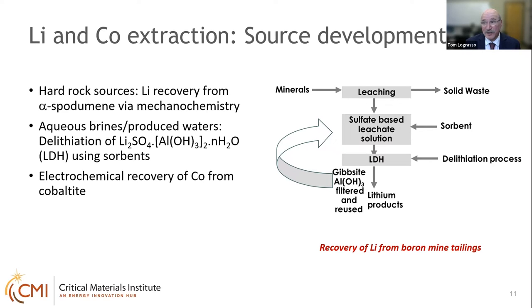For hard rock sources, it has to do with the... I have a slide. I'll come back to that. For the brines and produced waters, it's the effective separation of lithium, usually from sodium and potassium, which is also contained in these brines. So we've developed sorbents to effectively absorb the lithium and then to delithiate that on demand and concentrate it through a forward osmosis membrane process.